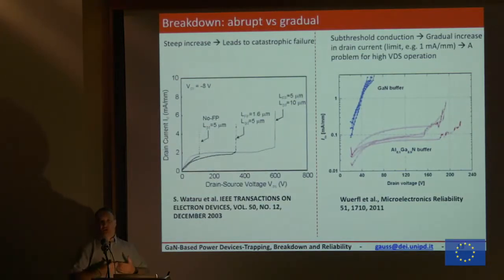The reason is that we don't really have avalanche today, and the reason is that we have multi-layer structures. The GaN is very strong, but what we have below and on top, the silicon below and the passivation on top, have a much lower breakdown than the gallium nitride. And the weaker layer will fail first. So we are not able to see the real gallium nitride avalanche breakdown, because before seeing that, we have the breakdown of the passivation or of the underlying layers.